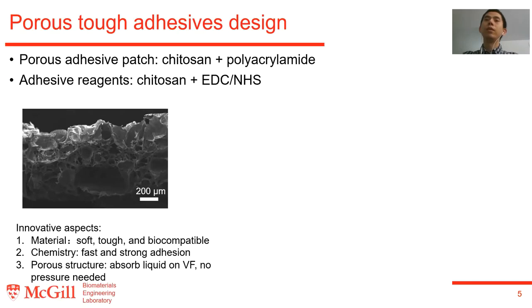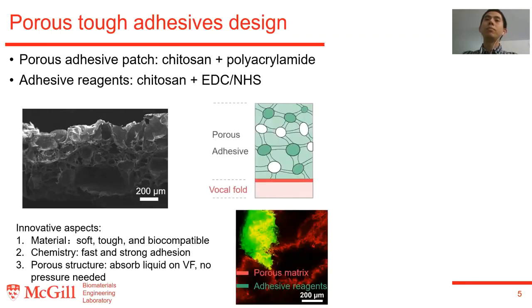We first fabricate a double network hydrogel made of chitosan and polyacrylamide. We then use freeze drying to create porous structure inside the hydrogel, as you can see from the SEM image. The hydrogel patch can effectively dissipate the energy under deformation. We then partially fill the pores with the adhesive reagent solution, which is composed of chitosan, EDC, and NHS. We purposely left some of the pores unfilled, so the adhesive patch is still partially dry.